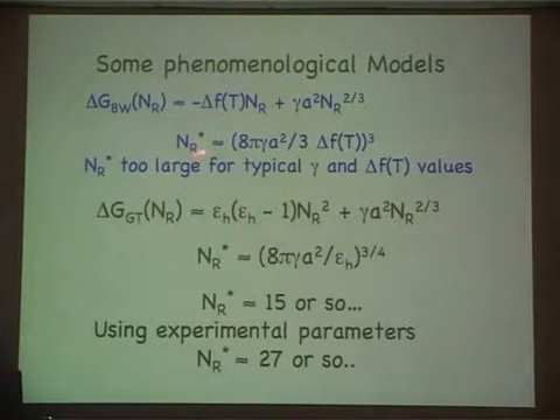So you do the usual minimization game, then it says that the critical nucleus in this picture goes by this little formula, and there are some numbers that are available with very large error bars for gamma and smaller error bars for this analog of the chemical potential. When you put them all in here, this number turns out to be very large for whatever reason. So this can't really be NR, it's probably going to be something less than that. We said, this is our work from some time ago, we said, look, the driving force really is hydrophobic collapse, and